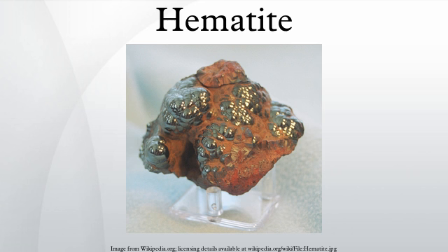Magnetism. Hematite is an antiferromagnetic material below the Morin transition at 250 K, and a canted antiferromagnet or weakly ferromagnetic above the Morin transition and below its Néel temperature at 948 kelvins, above which it is paramagnetic. The magnetic structure of hematite was the subject of considerable discussion and debate in the 1950s because it appeared to be ferromagnetic with a Curie temperature of around 1000 kelvins, but with an extremely tiny moment.